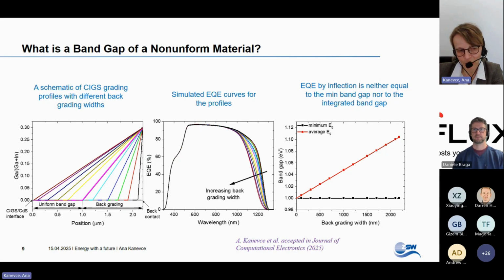If I think that EQE will give me a minimum bandgap, now all of these grading profiles will have a 1 eV bandgap. Another assumption is, normally when the absorbers are made, they go through X-ray diffraction, and this gives me a material composition, the integrated or average material composition. So for those graded profiles, this would be the bandgap determined from the integrated GGI value.